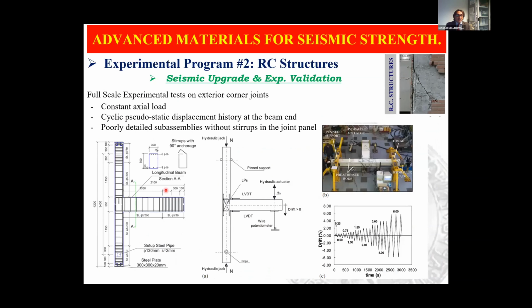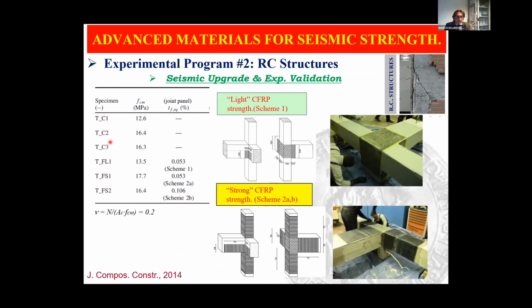So this is the specimen details with no stirrups inside the joint, as commonly happens in existing buildings. And this is the load history applied by the actuator in terms of drift, which is the displacement over the beam length. So what we did was 6 tests, 3 on control specimens, so without strengthening solution, and 3 on specimens strengthened by using the FRP.